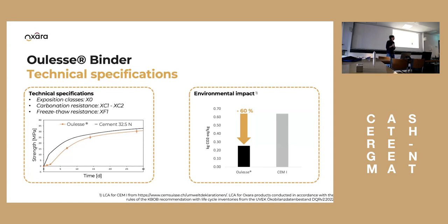And in terms of strength, you can see a strength development curve here. The orange curve is the Oulesse binder, and the other one is a cement 32.5 of that strength class. The main difference is that in the early age strength phase, so in the early days, the strength development of our binder that we are currently developing is lower. So that can elongate the demolding times that you have for your walls.